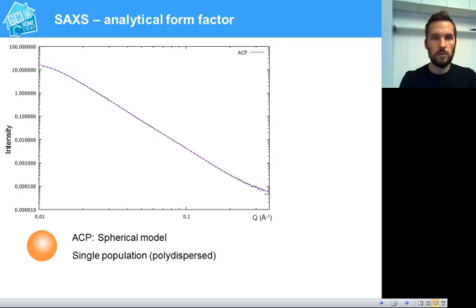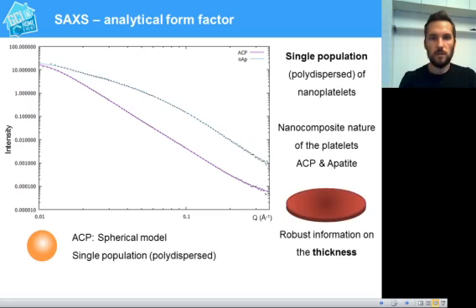At first, we measured the amorphous material, and the experimental trace was modeled with a single population of spherical nanoparticles. Conversely, the sample at 24 hours was modeled with a single population of nanoplates. This means that these nanoplates are a composite material formed by an amorphous and a crystalline phase, because no traces of spherical particles were detected in this sample.